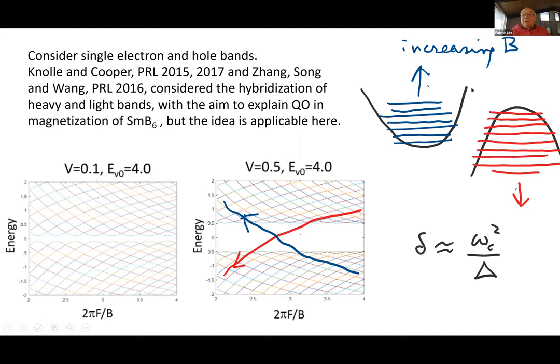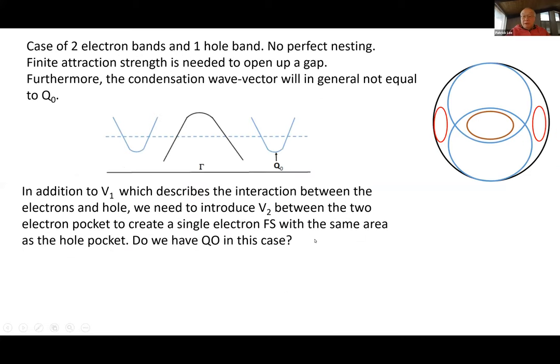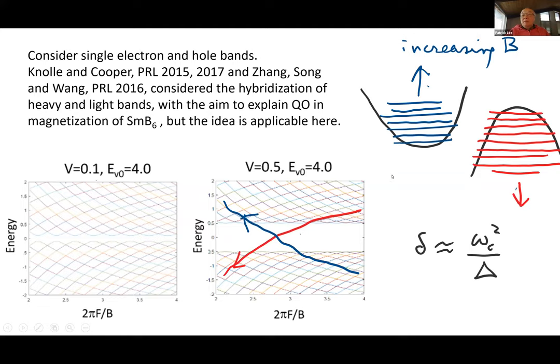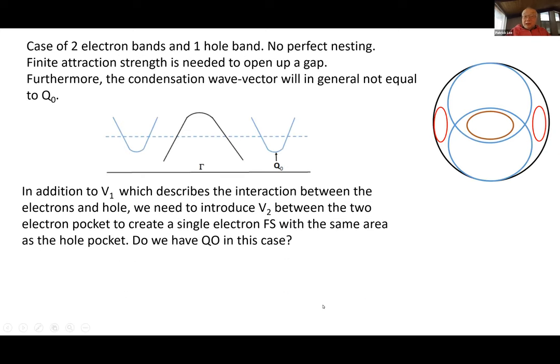The idea is you have an electron band in a magnetic field—this becomes quantized. Your hole band quantizes in the magnetic field. These guys move upwards and these guys move downwards. Then at the Fermi level these things can cross, and when they cross they hybridize. As a result you get these scallops coming in like that, so you get quantum oscillations. This is a very natural way to get oscillation in the gap magnitude. The size of the oscillation is actually the square of the cyclotron frequency divided by the gap itself, so it could be small.